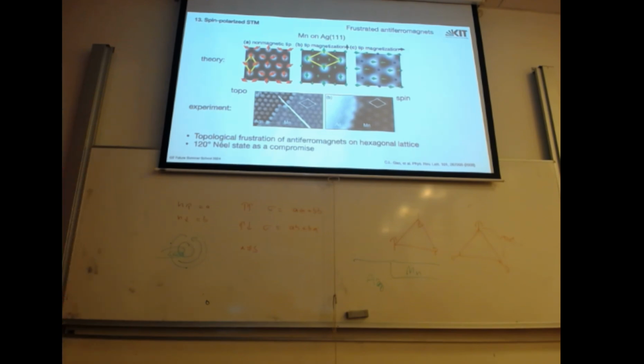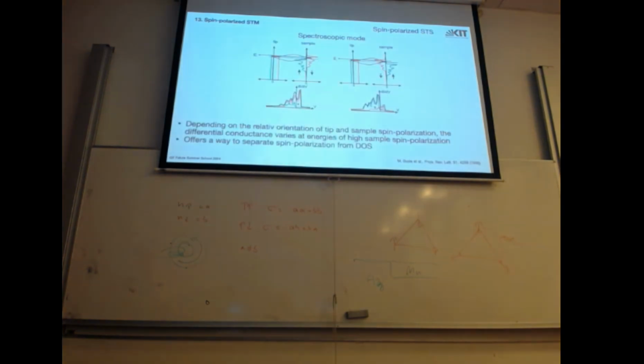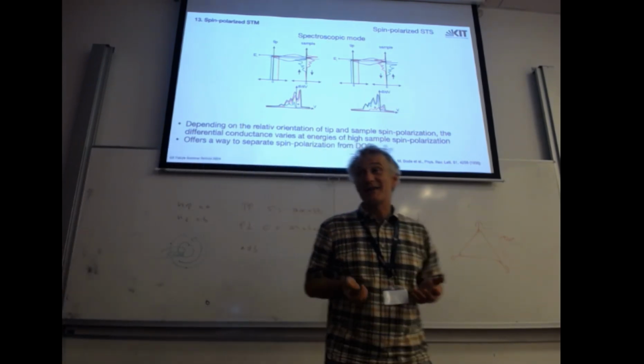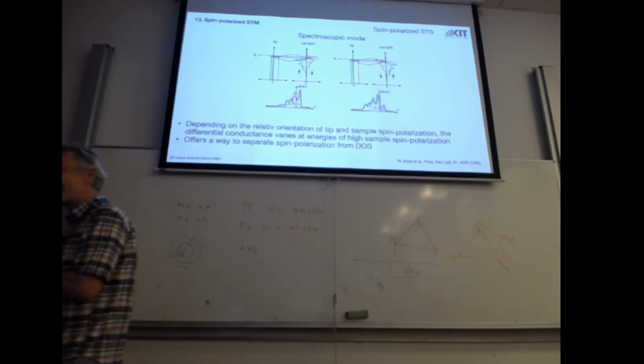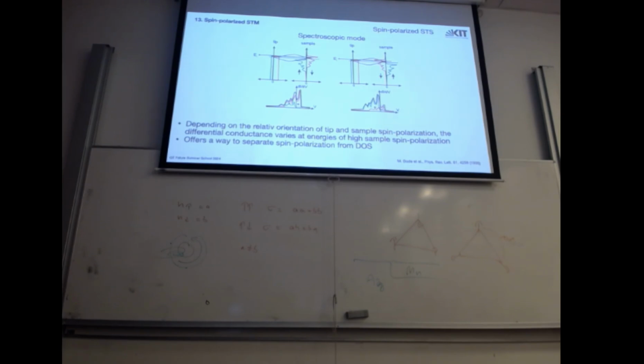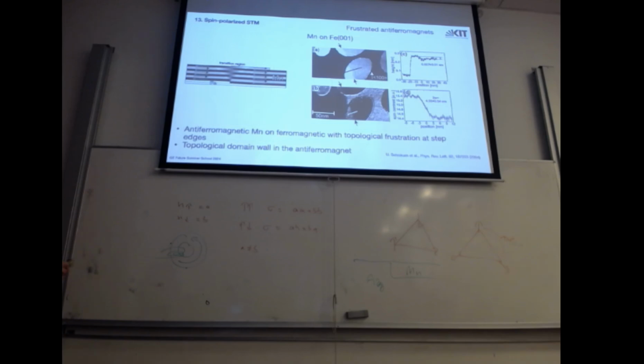Just to make sure that I understand things correctly, when you say that you measure polarization, you mean the difference in density of states of spins polarized in one direction and another direction, right? In the end of the day, you still measure the density of states, but for different spins. You don't measure the magnetization itself. There is no magnetization. You measure spin polarization. Yes, sorry, very often we say magnetization, but in principle it's all spin polarization. But for normal materials, the spin polarization is collinear with the magnetization. So you have maximally a minus sign. Yes. Okay. You got me? Okay, then we continue.